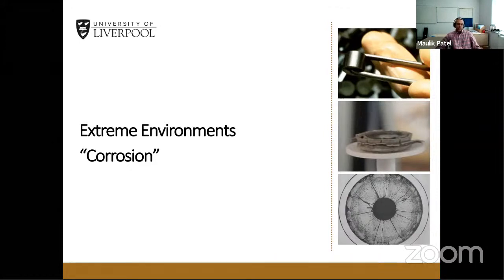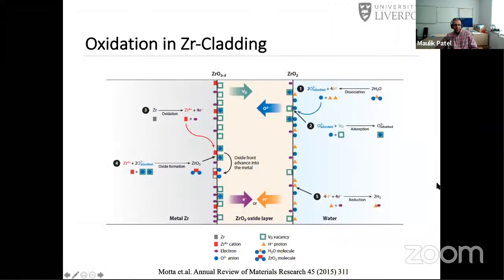So I'll move on to the last one, which is corrosion, which I didn't want to talk much about, so I kept it at the very end. These cladding rods are made of zirconium, and it's one of the worst materials for the functionality it should be best at, because these cladding rods are dipped in water, and zirconium loves to get oxidized if you heat it up.